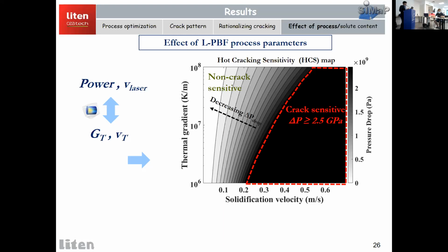So as you move away from this black region, you tend to be in a non-crack sensitive region, which gives you decreasing pressure drops. Okay, so this is what our model suggests. But whether it is in line with our experimental observations or not, we checked the crack density of the optimized sample and superimposed it onto this HCS map. We found that the crack density of 19 per millimeter square was just along the interface where you have the transition from crack sensitive to non-crack sensitive.